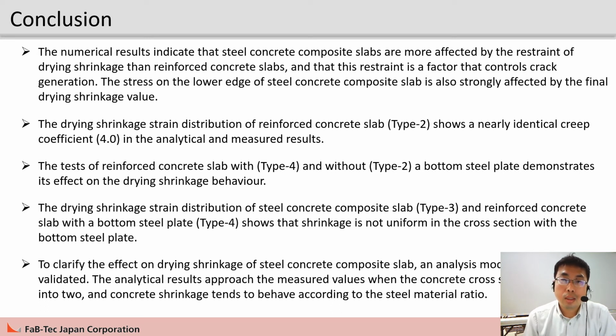The numerical results indicate that steel concrete composite slabs are more affected by the restraint of drying shrinkage than reinforced concrete slabs, and that this is a factor that controls crack generation. The stress on the lower edge of the steel concrete composite slab is also strongly affected by the final drying shrinkage value. The drying shrinkage strain distribution of reinforced concrete slab type 2 shows a nearly identical creep coefficient 4 in the analytical and measured results.